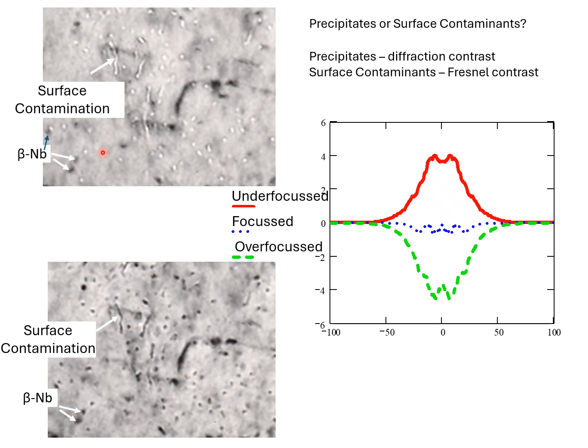So I've seen so many instances in publications where people see these white dots and say, oh, look, this is Fresnel contrast. We do it through focus imaging, therefore it's a cavity. No, it could be surface contamination.